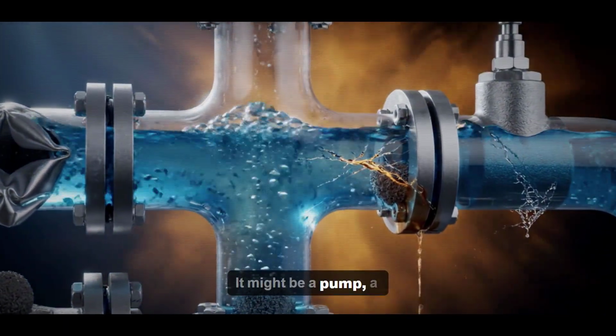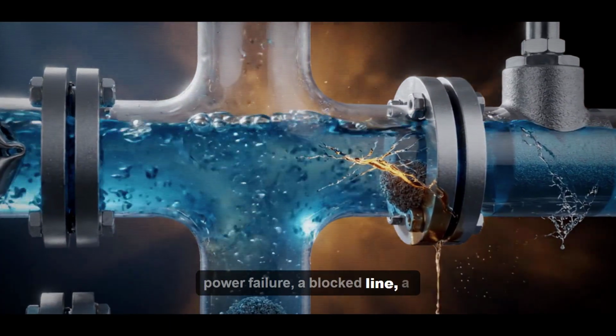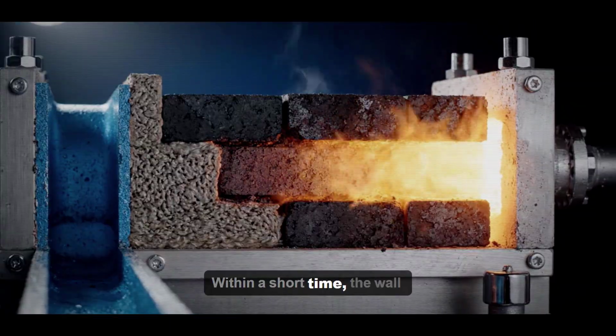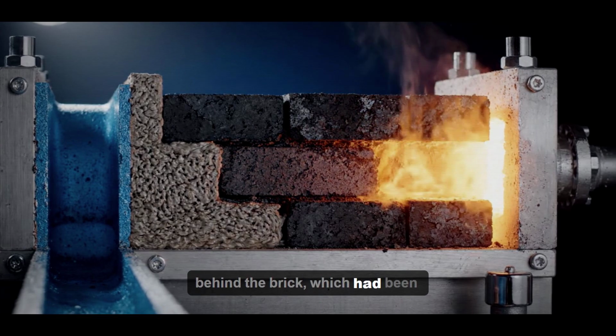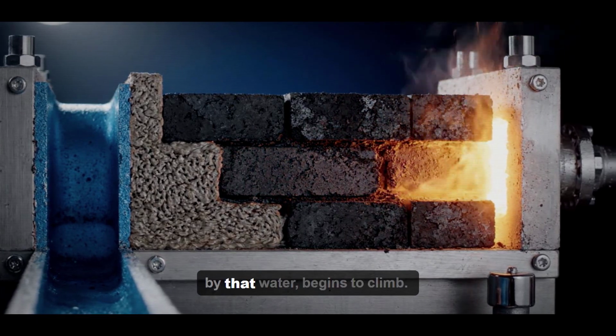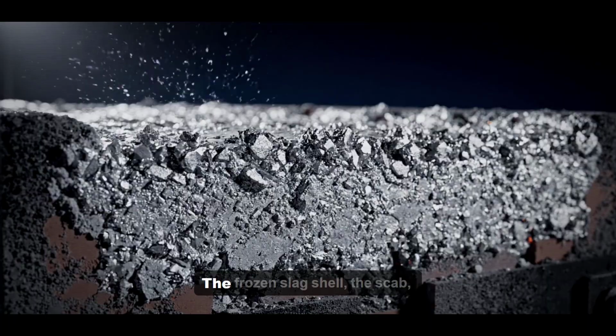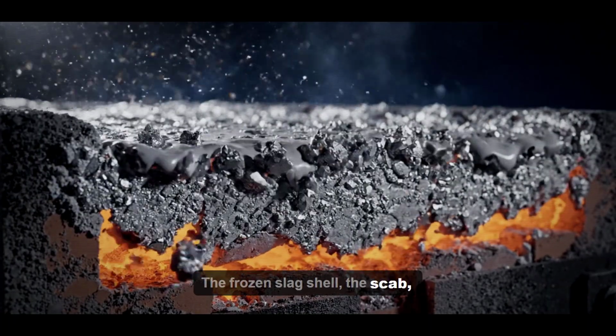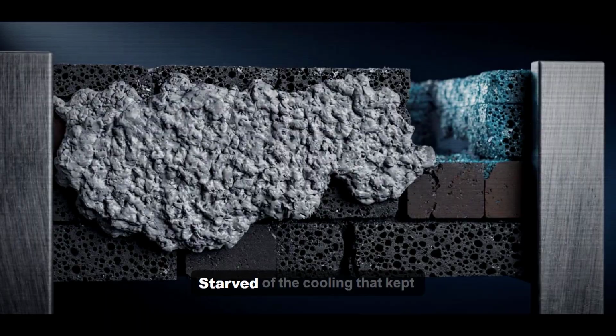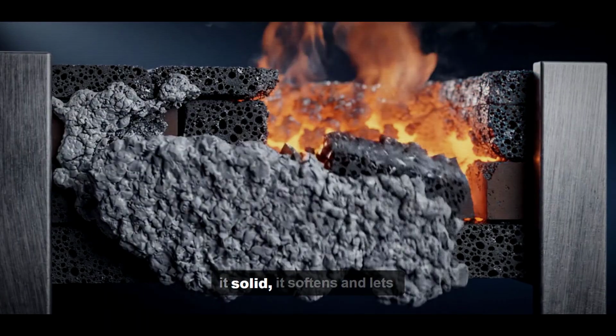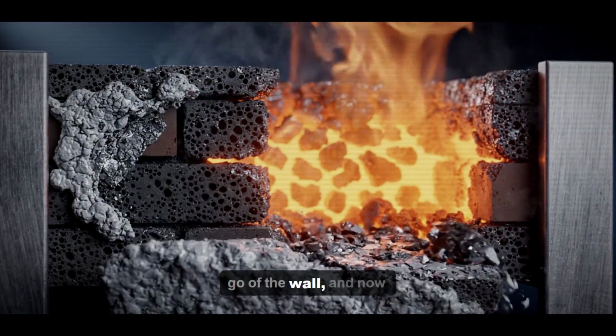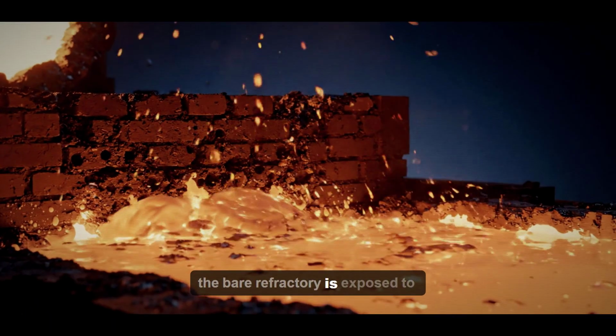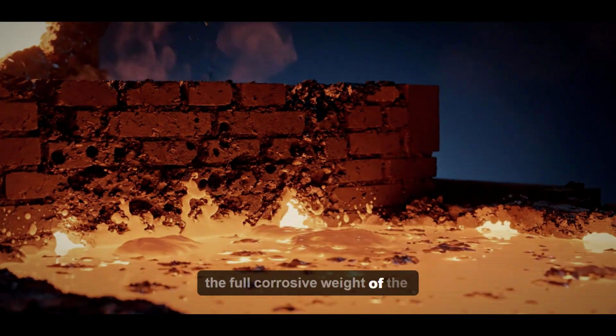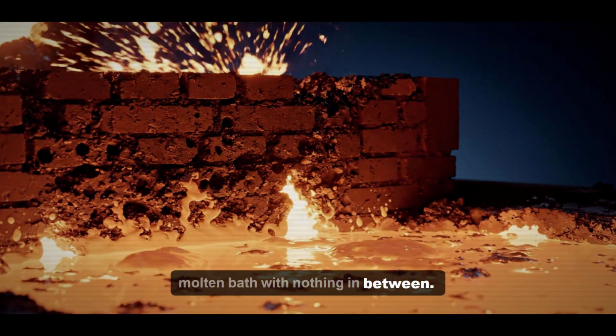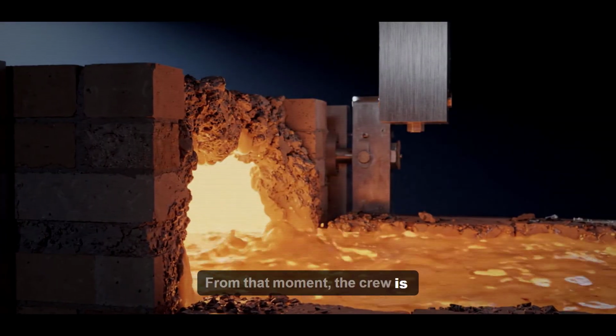It might be a pump, a power failure, a blocked line, a leak. Within a short time, the wall behind the brick, which had been held down at a safe temperature by that water, begins to climb. The frozen slag shell, the scab, is the first thing to go. Starved of the cooling that kept it solid, it softens and lets go of the wall, and now the bare refractory is exposed to the full corrosive weight of the molten bath with nothing in between. From that moment, the crew is racing the wall.